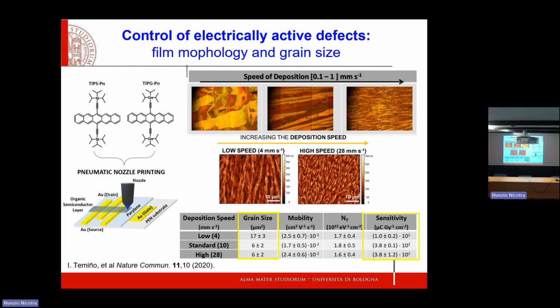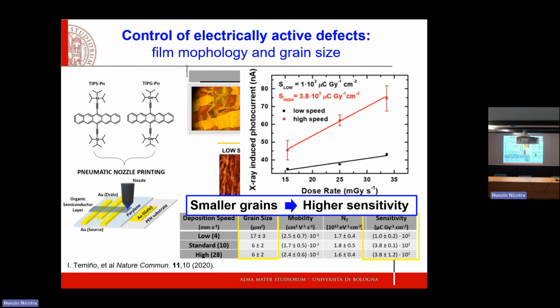What is interesting is that the mobility does not change much. Look at the low and high speed, same mobility, but the sensitivity increases 4 times. So something is really telling us that the grain size makes a difference. And please note that the higher sensitivity is achieved for smaller grains. Smaller grains means greater surface area and larger number of electrically active traps that can interact with your incoming charge-generated pairs.